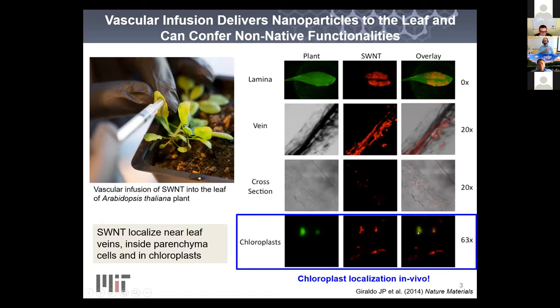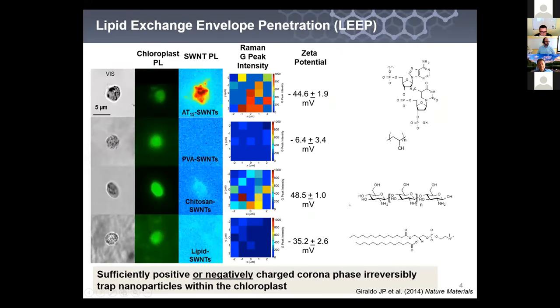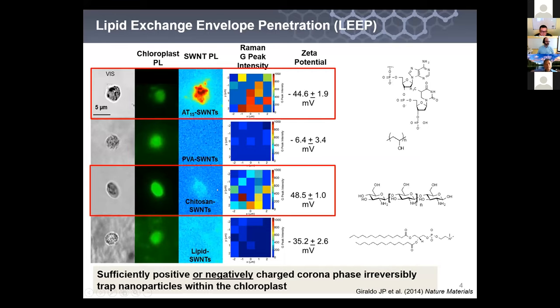And so this ability to traverse this series of membranes and biological barriers is unprecedented up to this point, and we're very interested in how this can happen. I have a lot of data. I'm going to condense it for you, but basically, nanoparticles that are strongly negatively charged or positively charged can actually show this. So these happen to be carbon nanotubes wrapped in DNA. They have a negative zeta potential, and they will traverse these lipid bilayer membranes and go right into the chloroplast. But chitosan-wrapped carbon nanotubes are positively charged, and will do the same thing.